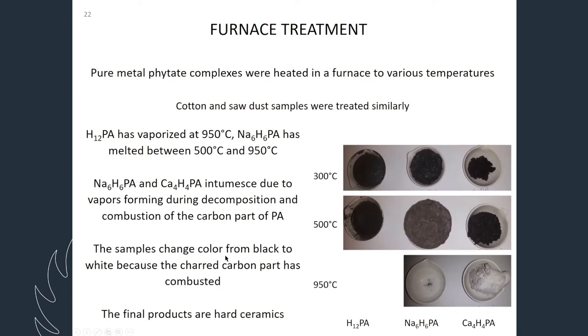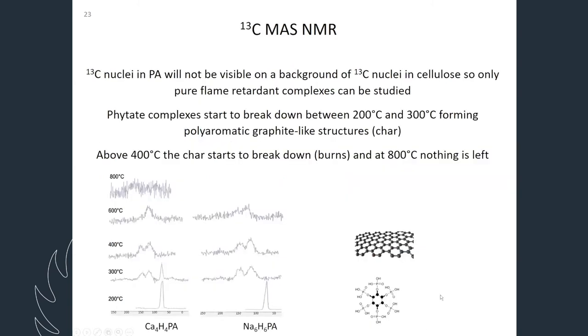The samples change color, as I described earlier, from black to white, because the charred carbon part has combusted. So as you go higher and higher temperature, the carbon content is decreasing. So for sodium, the process occur much earlier. And finally, it become a really hard ceramic material. So I cannot take it out easily. There is still quite a lot remains, the sodium salt. So I have to really crack the heating vessel. And then the part comes out as a nice crystalline material when the ceramic things are formed. Yes, now I give it back to Anakari.